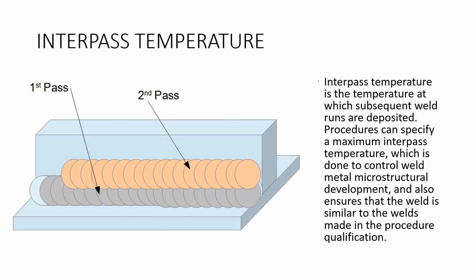Or some materials, we don't weld on them unless they're above a certain temperature. So a lot of this is done to control the weld metal microstructure, and it also is going to ensure that the weld is similar to the welds that were made in weld qualification when we wrote our weld procedure. So sometimes we have a maximum interpass temperature and a minimum interpass temperature. We don't want to put too much heat into a material and ruin its mechanical properties, or we don't want to put too little heat into it and ruin its mechanical or chemical properties.